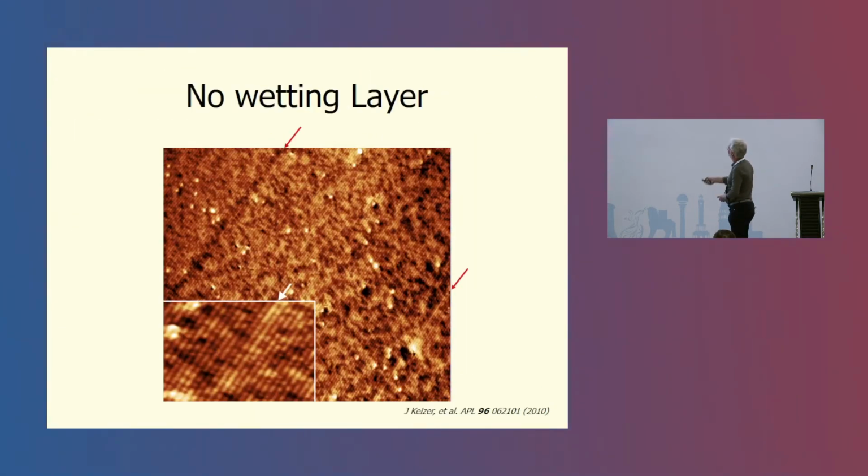Again, I show here a little bit of the wetting layer. You see it's very weak, so indeed these droplet dots produce hardly any wetting layers. This is also very important if you look at the luminescence from the quantum dots, because the luminescence can couple to the wetting layer, and that is seen as a disadvantage.